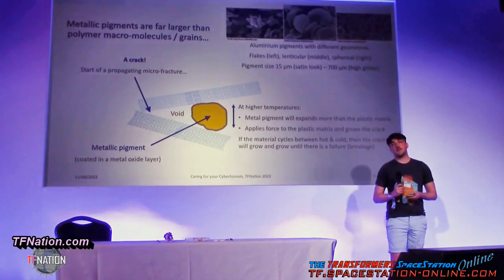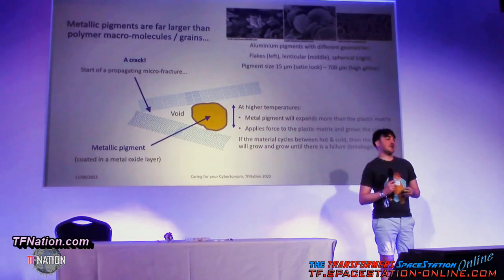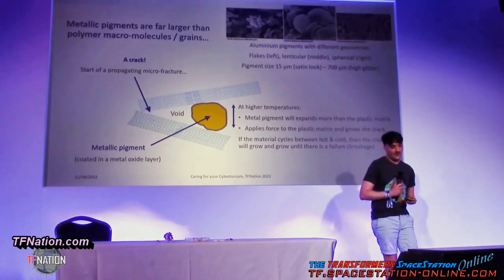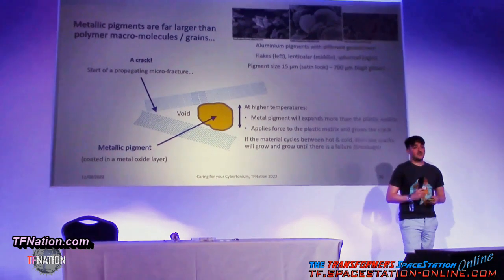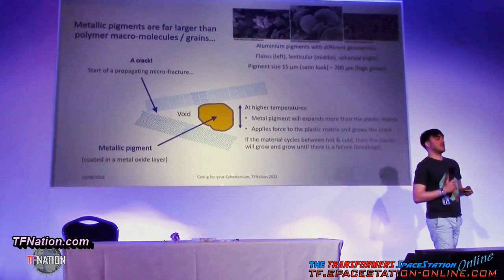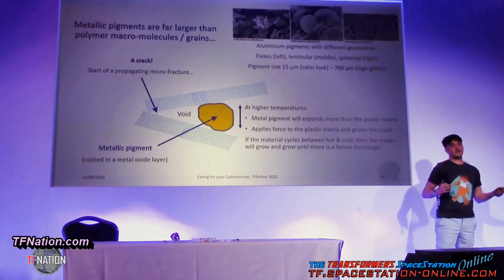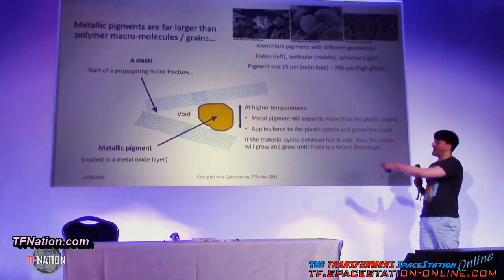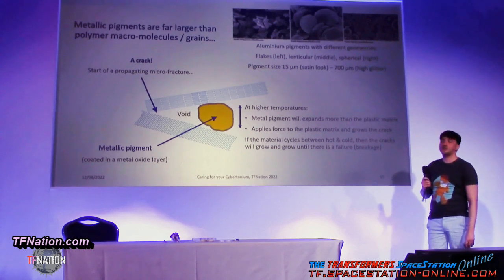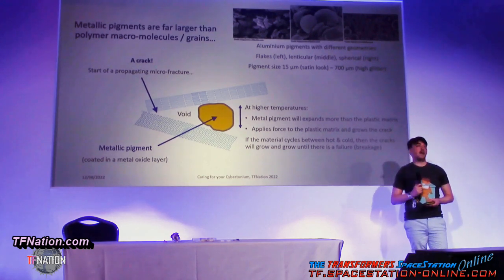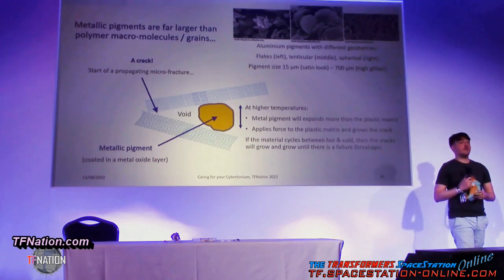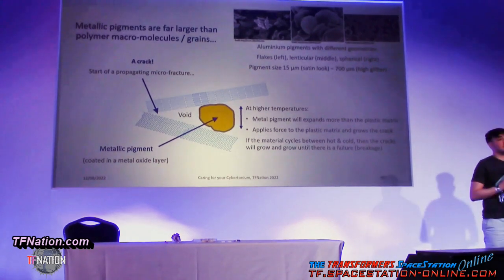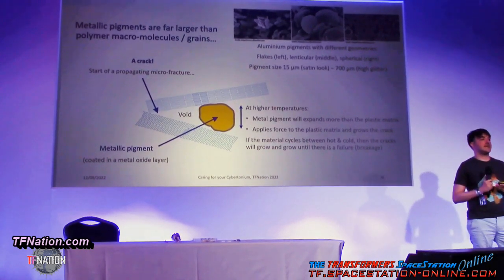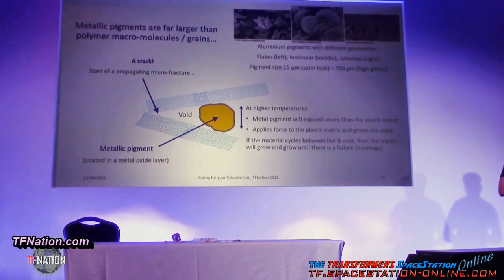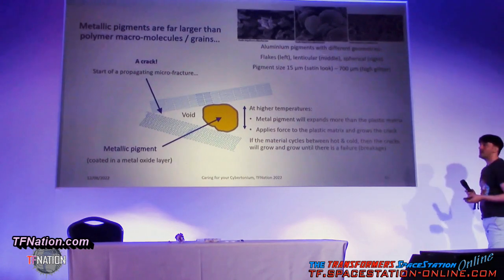Now, remembering that atoms are down in angstrom scale, they are very, very small. Essentially what happens is you have these incongruities, these discontinuities in your plastic matrix. So like you can see, we have aluminium there sitting between two grains of opaque plastic. Now between those grains, there can be voids. Voids mean, especially between two grains, you can form a crack. Stress loves to build up at interfaces. So that's why plane windows are circular and not with corners.